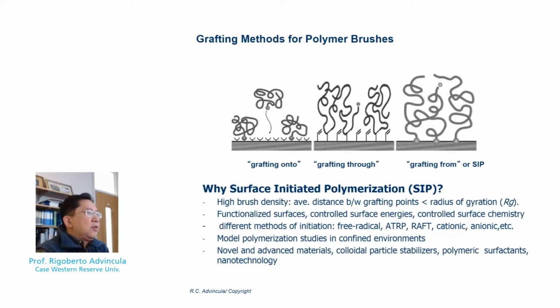Now, let us try to distinguish grafting methods based on either physisorption or chemisorption. Where we have an existing polymer chain with a group that is chemically or physically bound to a surface, we simply call that a grafting onto approach. Where we do polymerization such that the initiation takes place in the bulk, and during polymerization it stitches through or grafts through surface-bound monomer species, then we have a grafting through process. However, what perhaps enables the formation of high grafting density chains better than the first 2 is what we call a grafting from method,